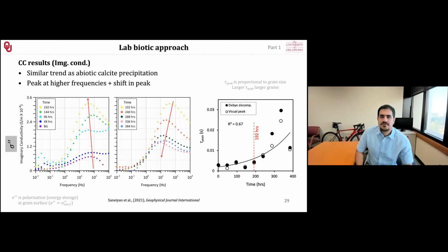But we are looking for our complex conductivity, or geophysical, geoelectrical signal, right? We were able to see a similar trend here, just like the previous experiment: we had no peak in the imaginary conductivity signal. And as we started treatment, the peak increased in magnitude and reached a maximum level, and then went down and reached a plateau. Very interesting, very similar to the previous experiment, but this time we reached a much higher magnitude compared to the previous one. So we had much more surface area produced by these microbes. Basically, they distributed everything much better than in the previous experiment. And then we had the same trend as the previous one.